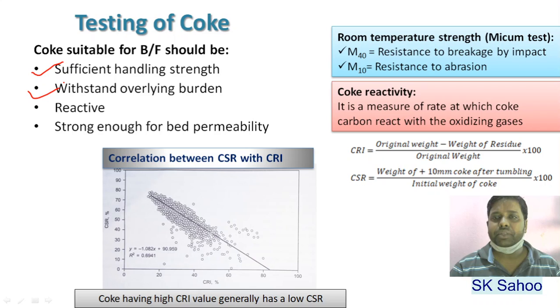So it has to withstand all the pressure, and also it has to be reactive enough to produce carbon monoxide as it descends from the top to bottom, because reduction is required. It should be reactive enough to produce carbon monoxide, and also strong enough after reaction to ensure permeability in the region below the cohesive zone, because at the cohesive zone the strength of all other raw materials is very less because they have been fused. So coke is the only raw material which has not been fused. It is only responsible for the bed permeability, so it should have enough strength to maintain the bed permeability to make the reduction feasible. Therefore, coke reactivity and its strength, both at room temperature and at elevated temperatures, are necessary to be assessed for its suitability.